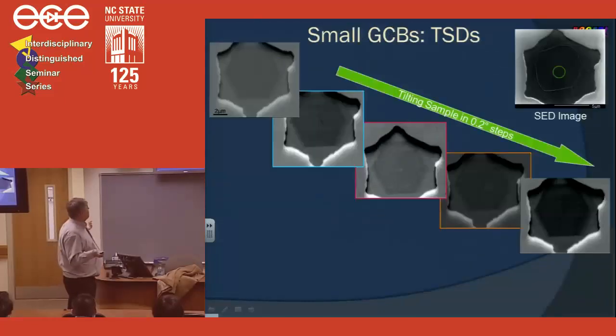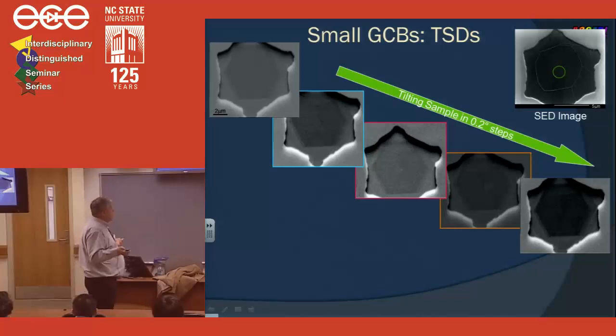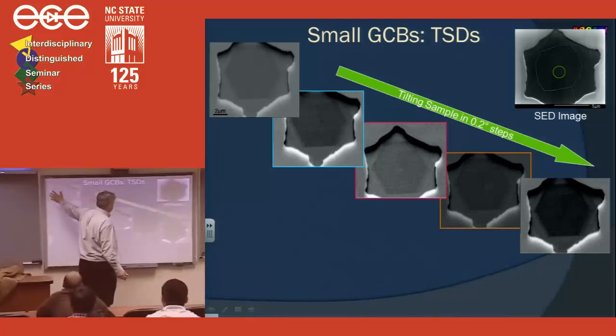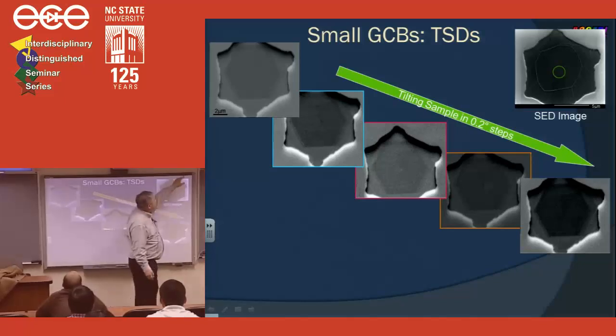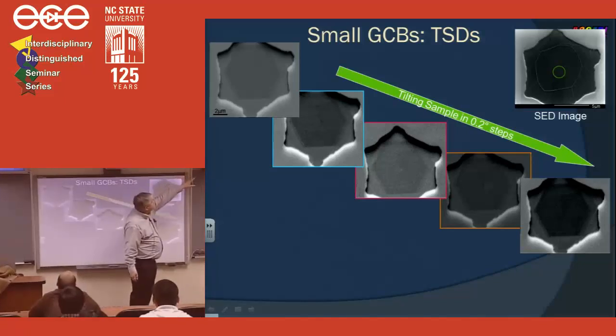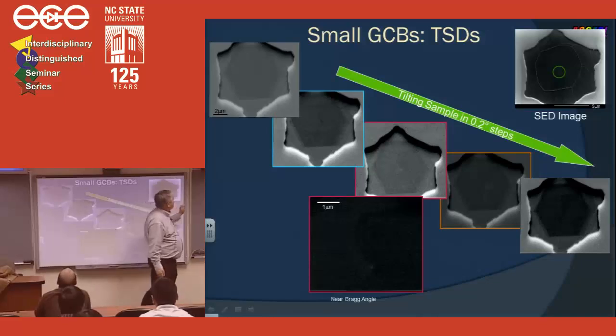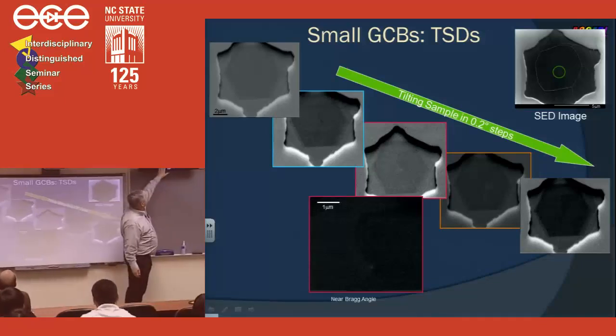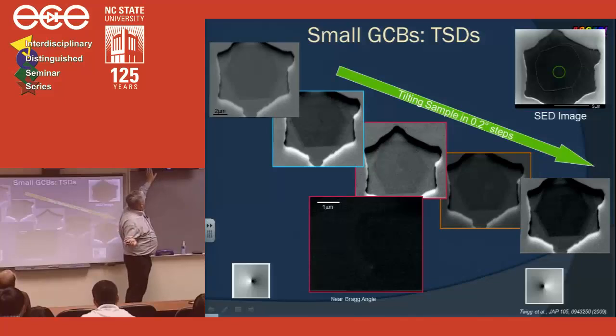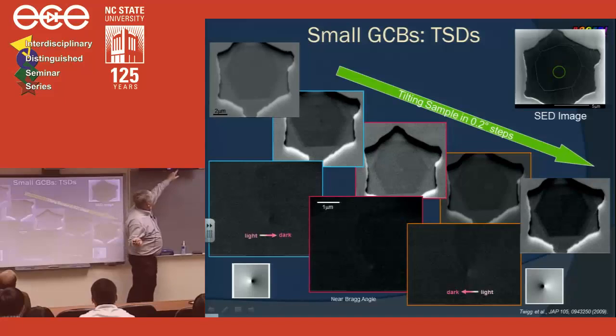So here's a particular graphene-covered basin, and we've changed the Bragg tilt angle of the sample, and we've gone from positive to negative values. You can't see it on this bottom image, but you can see in the top image that the contrast of that center dot is changing. Near the Bragg angle, you hardly see it at all. And as we go away from the Bragg angle, it looks light to dark, and on this side, it's dark to light.